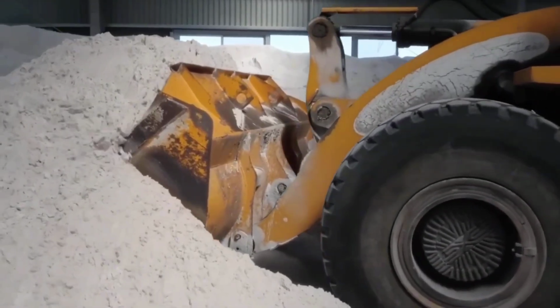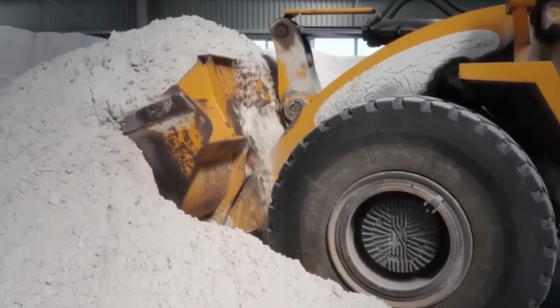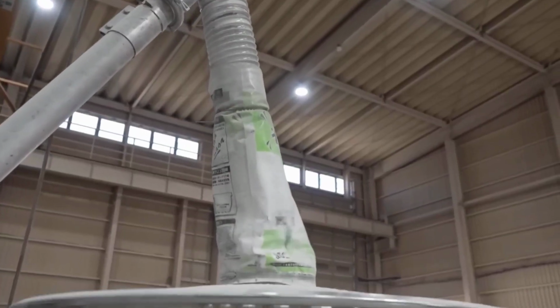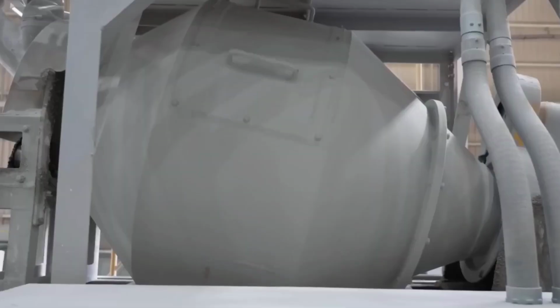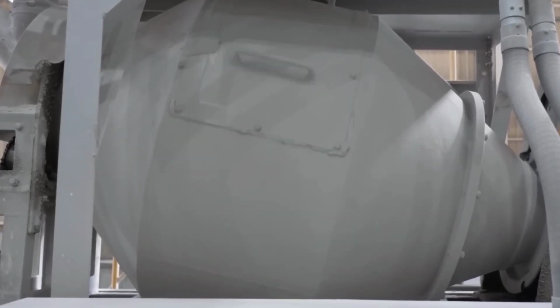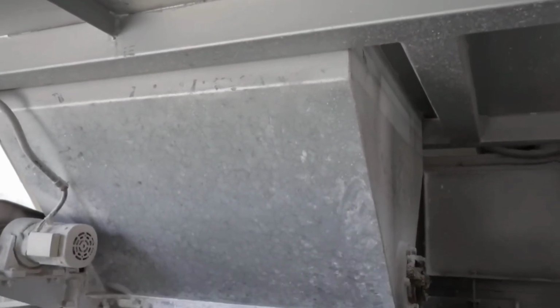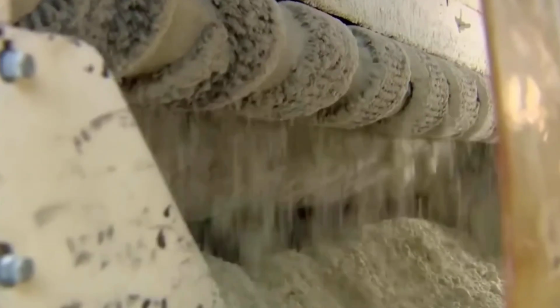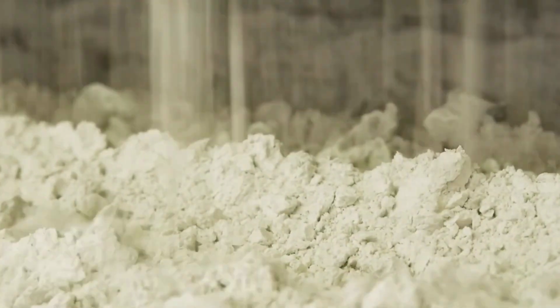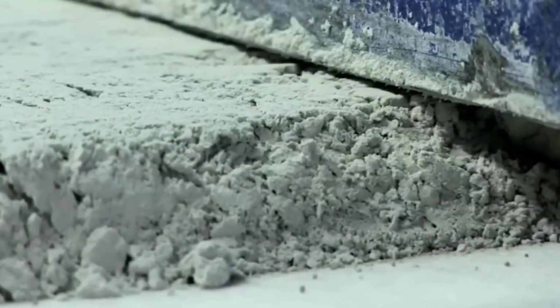The mixing ratio is extremely low, typically around 0.4–0.6% of the total glass weight, yet it determines the final material's density, porosity, and thermal insulation performance. During the melting phase, these foaming agents decompose and release CO2, forming millions of sealed air cells within the molten glass mass. To ensure consistency, the blend is slowly stirred by low-speed helical paddles that maintain even distribution and moisture control.